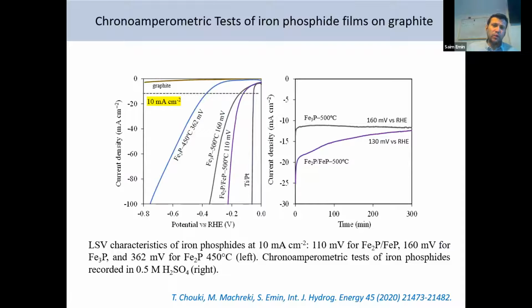Then we took these materials and tested them again in electrocatalytic studies. This time we were able to achieve an overpotential for hydrogen evolution at 10 milliamp per square centimeter of about 110 millivolts. This is in an acidic environment at pH close to 0. And this was achieved with a film heated at 500 degrees.